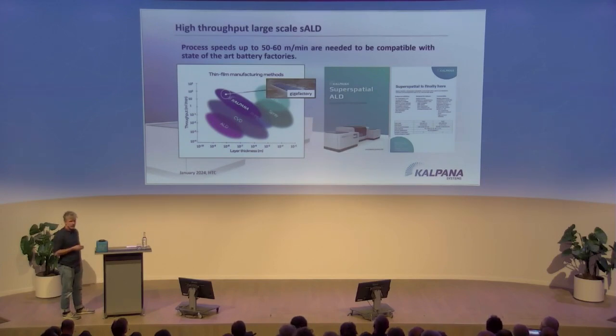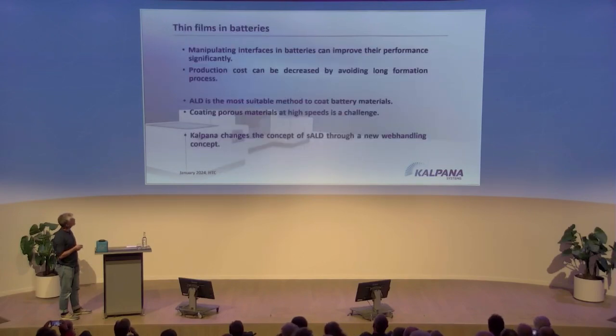And you need to go fast because when you look at high volume battery production, you usually should go up to 50 or 60 meters per minute of web speed. And this is what you really need to end up in a gigafactory. And we think we can reach that, so say coat 100 square meters with a few nanometers of coating, at least with the larger one of the two pieces of equipment that we're developing. Yeah, that's mainly all I had to say.